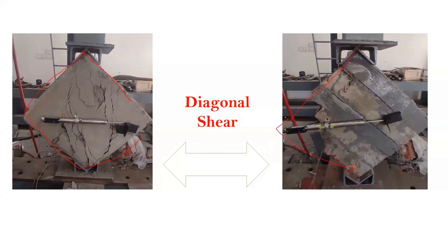So that's very, very important. When we choose FRP, we should choose FRP accordingly. Like the modulus of carbon is very high, modulus of glass is high, and modulus of BFRP is literally lesser than carbon. And strength also matters. Thickness of that FRP matters a lot. If you allow the FRP to yield, then we can expect a crack like this. So that is more advisable because we can get a desirable yielding pattern.